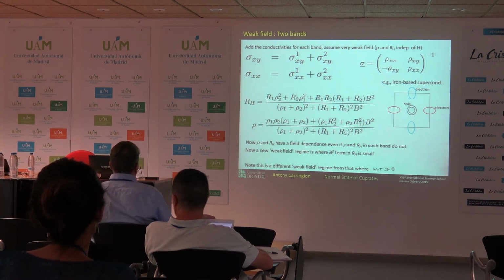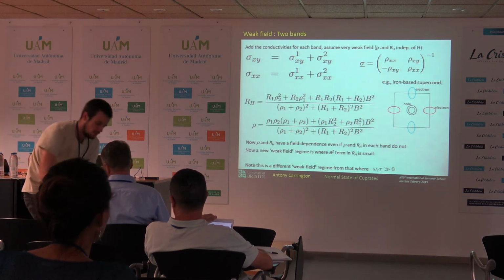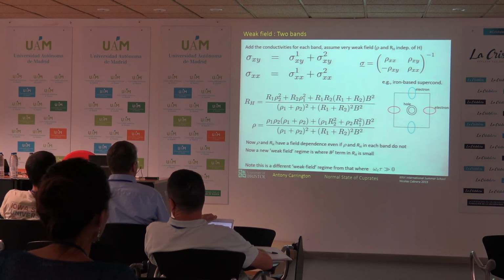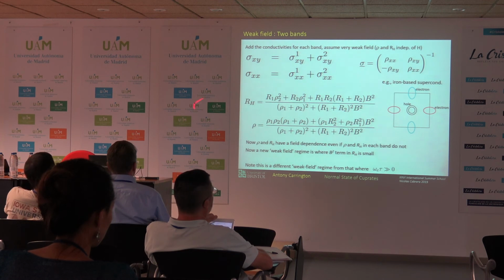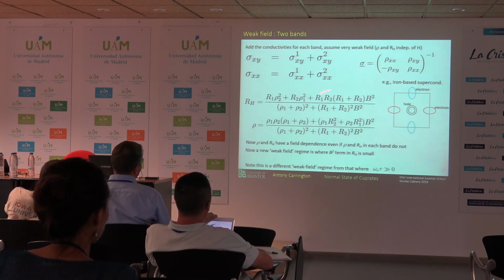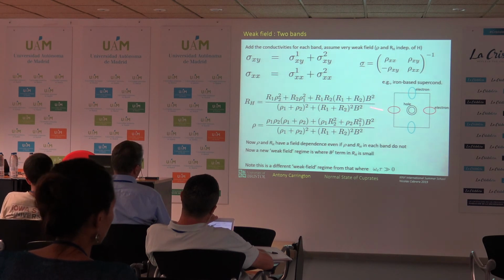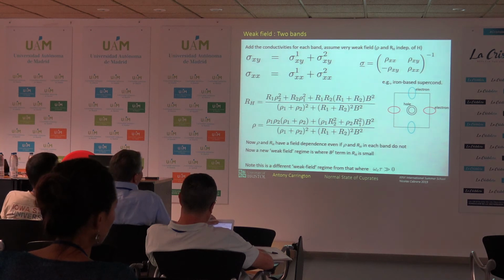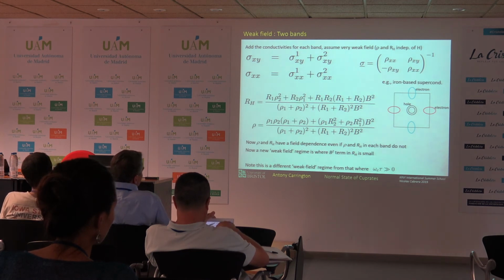So if you start off with a model where the Hall coefficient is independent of field, and the magnetoresistance is negligibly small, then when you combine the two bands, you end up with a Hall coefficient that now is dependent on field, and a resistivity that also is dependent on field. So often people then talk about the weak field and high field regime of this expression. That's going to be different to what I'm going to be talking about in a minute, which is when we're really going to go to the high field regime, where omega c tau is much greater than 1.